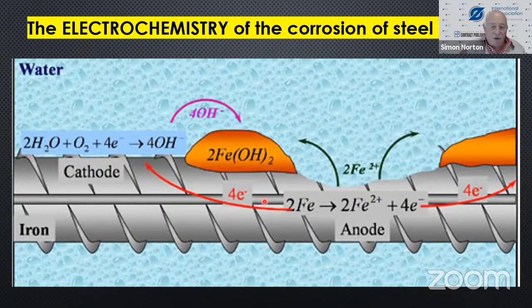We have 4 electrons. Those 4 electrons then move over to the cathode on the steel surface, and water and oxygen are reduced. If you have an ability to stop the cathodic reaction over here, then you halt the whole corrosion process. If you can halt this process over here, you also halt the corrosion process. And hence you would use things like galvanizing of rebar, or corrosion inhibitors, or corrosion passivators. But we're not going to be speaking about that. We're just talking about the generalized effect of water on steel.